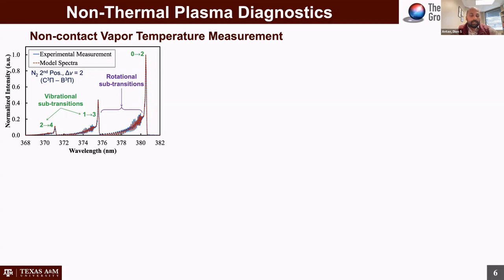This high energy phase of matter essentially emits light, and that light picked up by a spectrometer can capture the various energy transitions. So you're looking at vibrational, rotational, electronic excitation transitions, as well as in the particular non-thermal plasmas we're working with, there's very high rotational to translational relaxation, which allows us to make the assumption that the rotational temperature is about the same as the translational temperature, which is the way we estimate gas temperature in these systems.